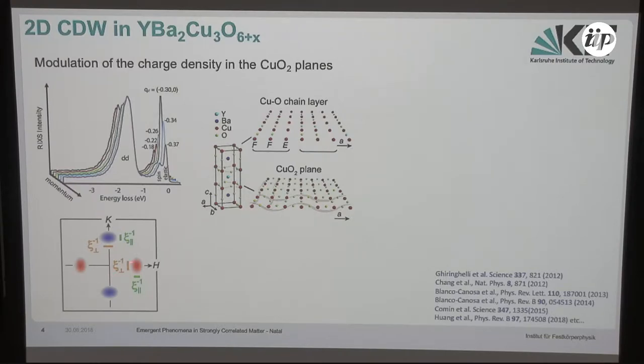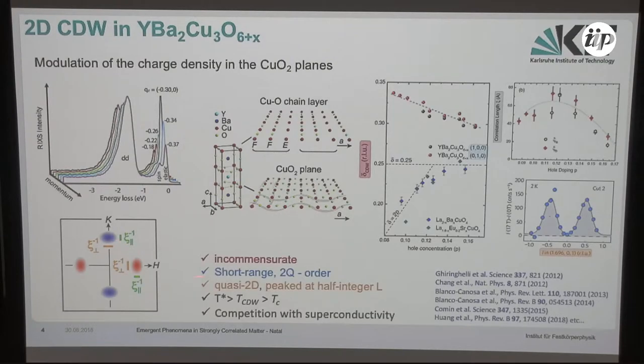So basically, it's an incommensurate charge density wave. It's peaked around 0.31 in reciprocal lattice units, and it is biaxial, so it's seen both along the A and the B direction. So the superstructure is roughly 3 unit cells large, but it's overall incommensurate. The maximum correlation lengths that you obtain are not terrifically large, something like 60 to 80 angstrom. So the question whether it's an actual short-range order, or if these are some kind of pinned long-range fluctuations, was asked from the beginning.